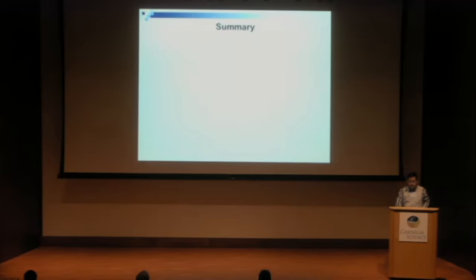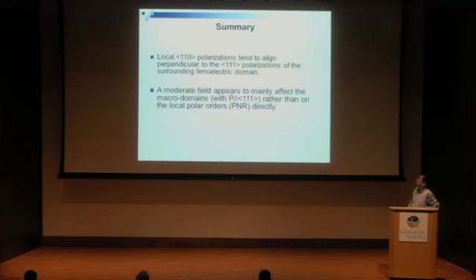And here is the summary of my talk. The local 110 polarization tends to align perpendicular to the 111 polarization of the surrounding ferroelectric domain. And moderate field appears to mainly affect the macro ferroelectric domain itself, which has polarization along the 111 direction, rather than the local polar order, the PNRs, directly. It's the end of my talk. Thank you for your attention.